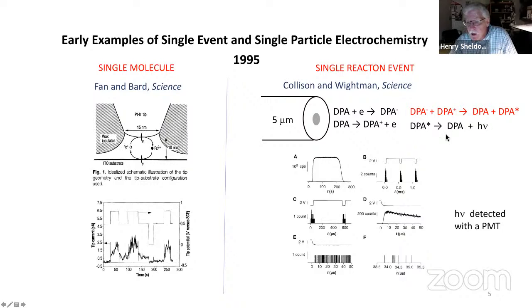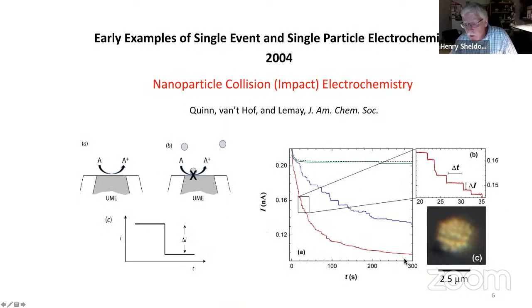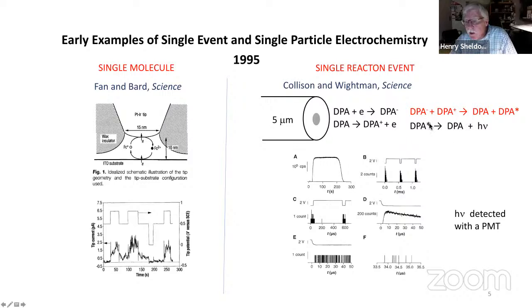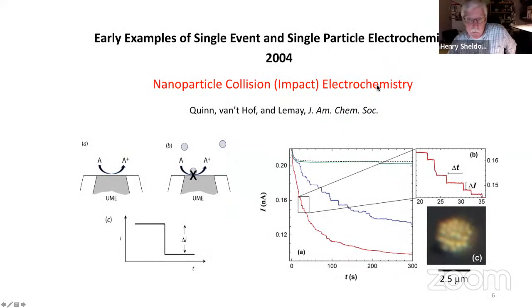That's the luminescence. And they showed that if you set this experiment up correctly, and you use fast time monitoring of the photons hitting a photomultiplier tube, they could see individual photons arriving, corresponding directly to this reaction. But what they were interested in is looking at the kinetics of this reaction up here. And so by using data like this, they were able to back out a rate constant for this reaction. And not surprisingly, it was diffusion control. So I think that's the first example of a single reaction being monitored.